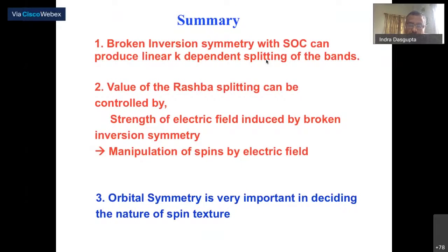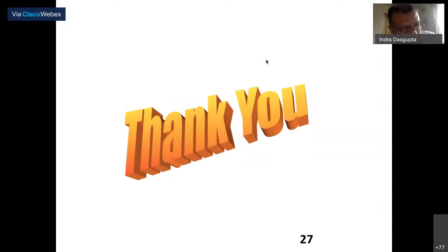Broken inversion symmetry with spin-orbit coupling can produce linear k-dependent splitting of the bands. The value of the Rashba or Dresselhaus splitting can be controlled by the strength of the electric field induced by broken inversion symmetry, and provides an avenue for manipulation of spin by electric field. But often the Rashba and Dresselhaus effects have been analyzed only by looking at the crystal symmetry, particularly non-symmorphic symmetry. We would like to point out that there is an additional symmetry people also need to take into account if they are looking at real systems and real materials. This is the orbital symmetry, which gives rise to the Rashba-Dresselhaus effect and plays an important role in deciding the spin texture. With this, I thank you all for your attention, and if time permits, I'll be happy to take some questions.